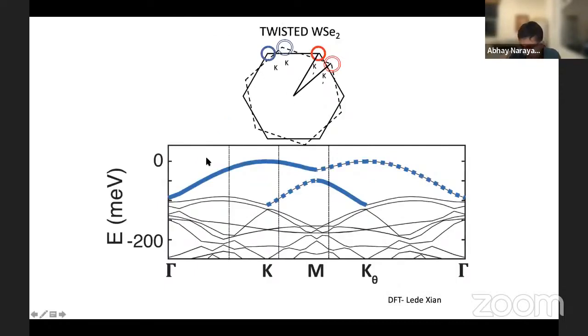And when you take 2 of these layers and you twist them relative to each other, here is a picture of what the band structure should look like according to theory. This is DFT theory. This looks at first sight somewhat complicated, but it's actually not that bad. If I look at this solid line here, this is the original valence band from one of the layers. If I look at this dashed line here, this is the valence band from the second layer. And when the 2 layers are touching each other, there's some hybridization gap that opens between the 2 layers. So that's the total band structure. Once again, all the physics that we are interested in happens when you're filling holes just in this topmost of the bands, and you shouldn't worry too much about all of these other bands.